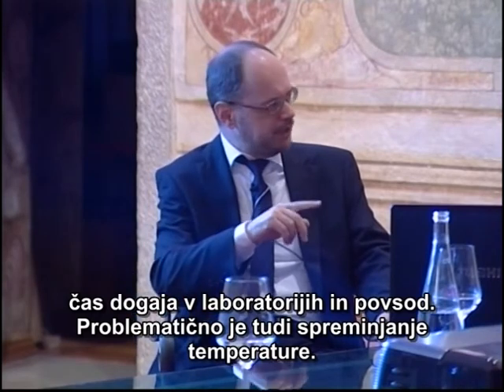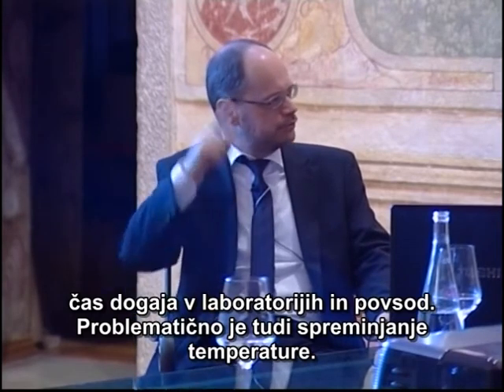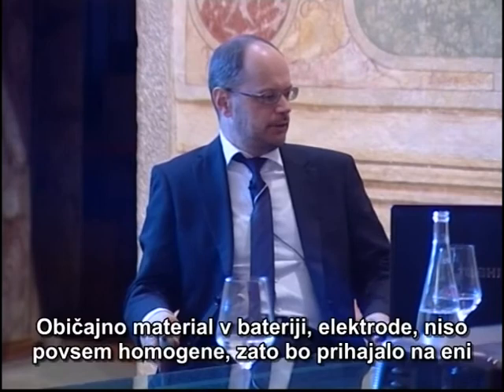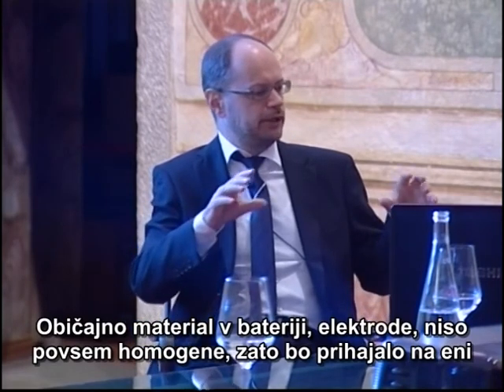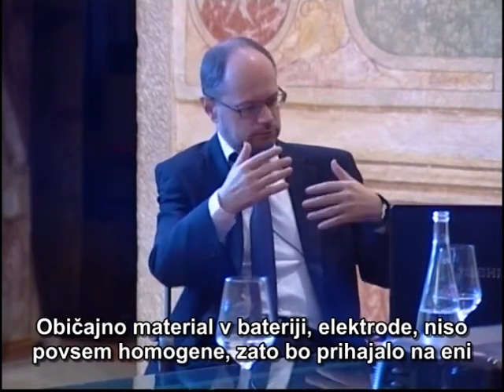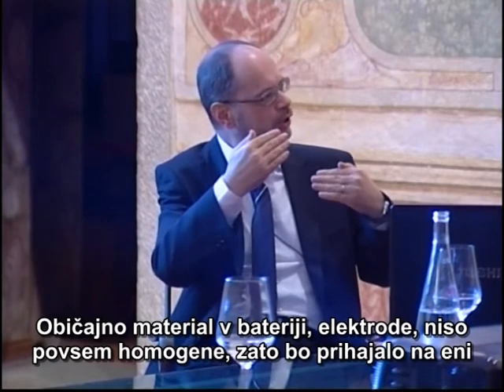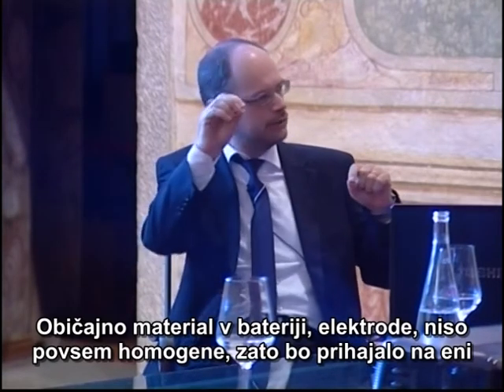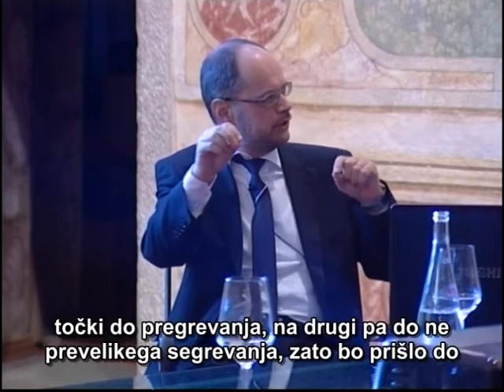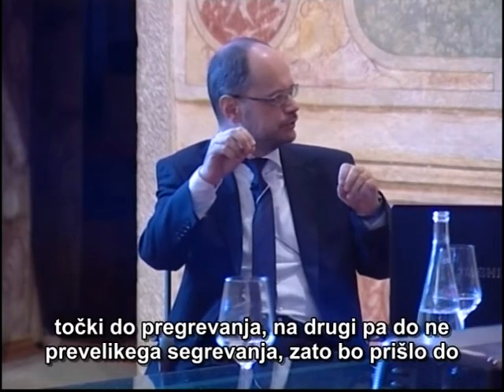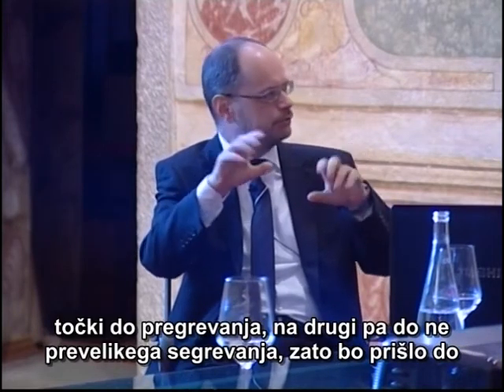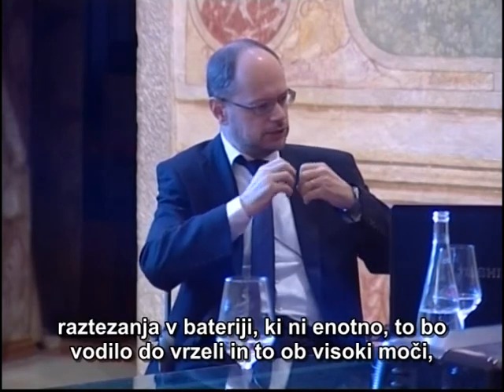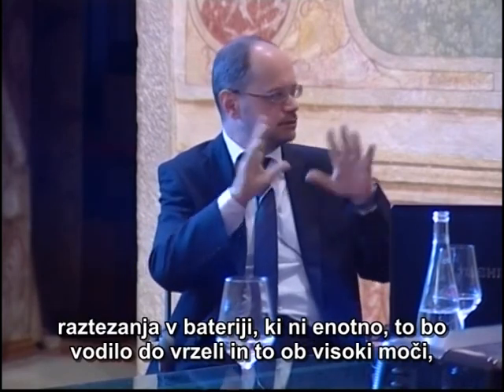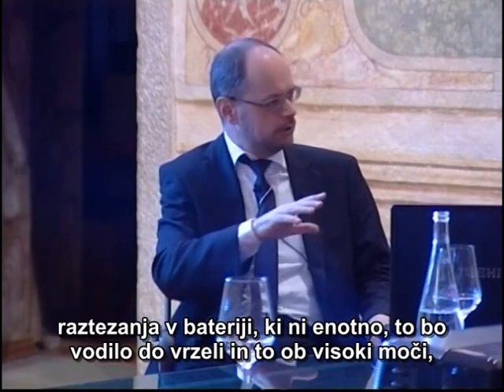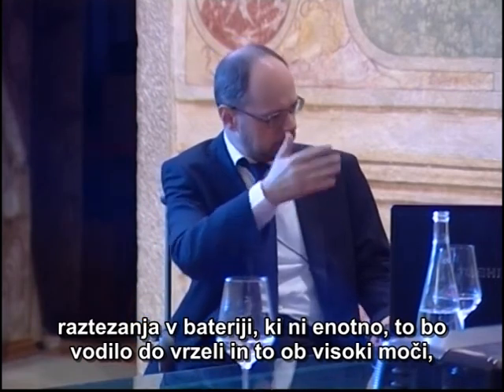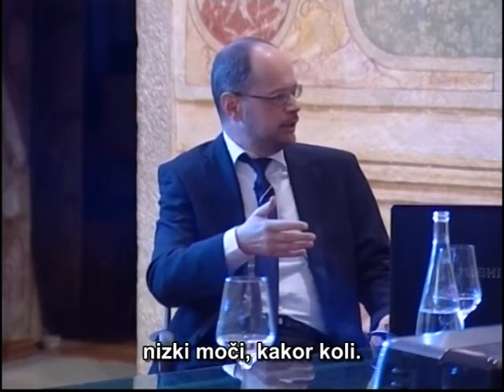Then the temperature is also a problem, temperature fluctuation. Especially because usually your battery material, your electrodes, are not completely homogeneous. So you will have overheating at one point and not so much heating at another. So you have some non-uniform expansion of your material, and this will lead to some cracks and whatever happens. This happens during high power or low power, whatever.